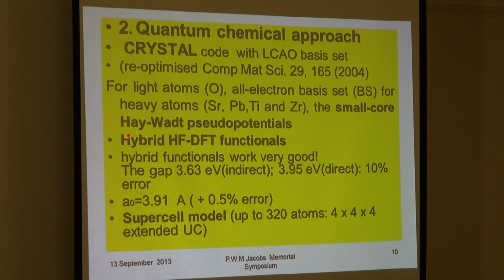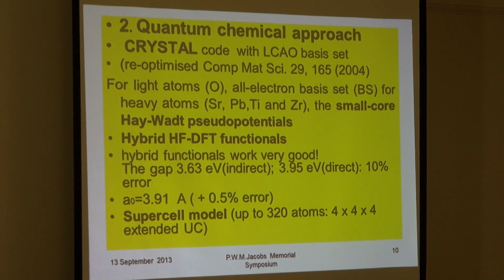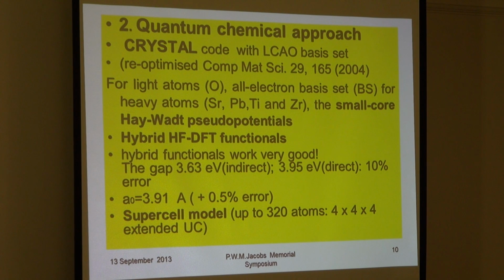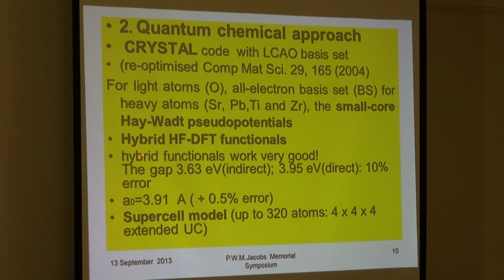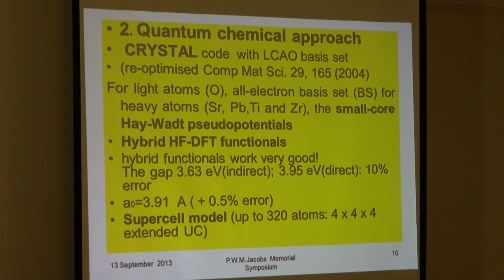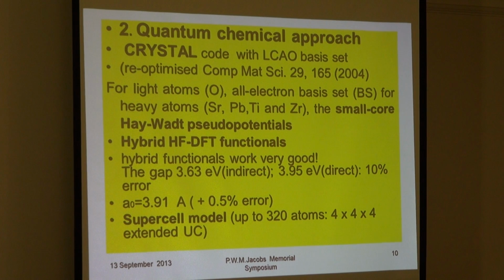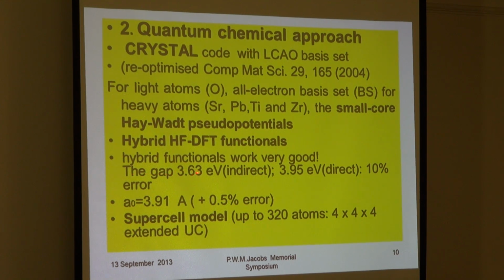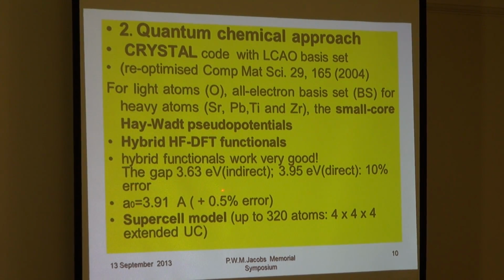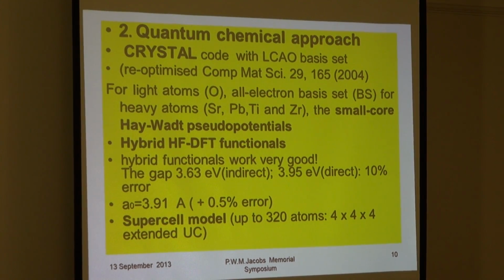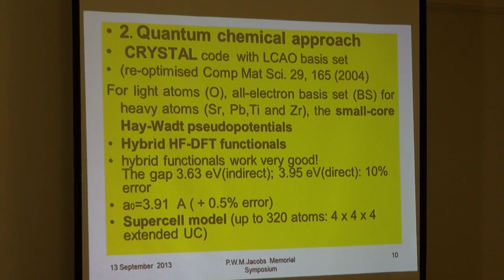And nowadays we could easily use in these calculations so-called hybrid functionals, which is important for calculations of defect properties because you need a very accurate band gap to put energy levels within the gap. A typical example is strontium titanate. If you calculate the Hartree-Fock gap, instead of 3.5 eV you have 6, and DFT gives you 1.5, so twice overestimate, twice underestimate. And with hybrid, you have an error of about 10%. So it's more or less good quality. And the lattice parameter and all this could be reproduced with 0.5% error. So we use a standard supercell model, which could be cubic or not cubic, extended with several hundred atoms.